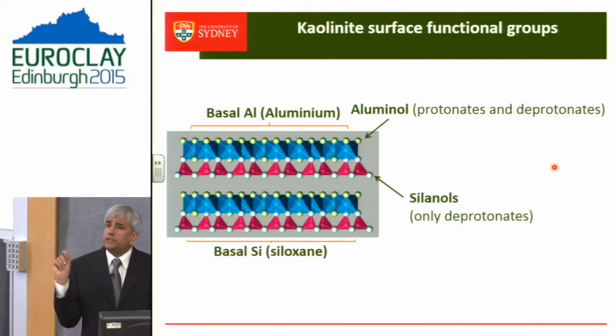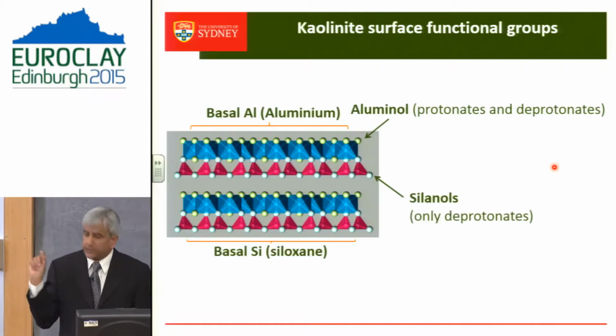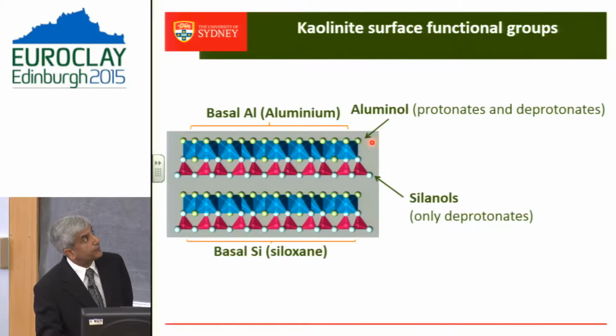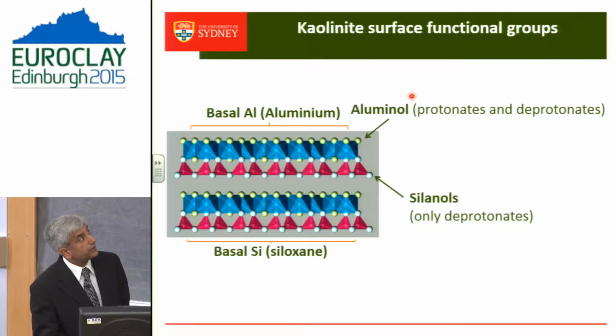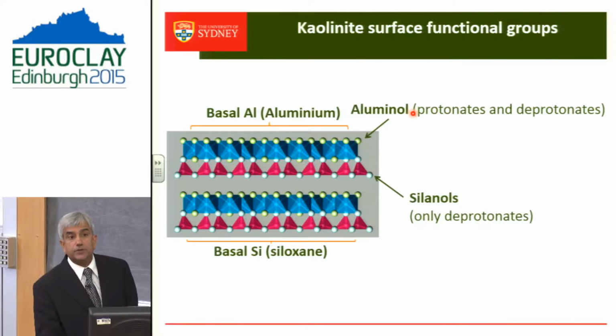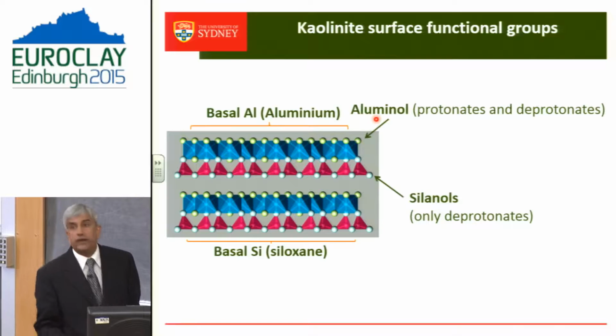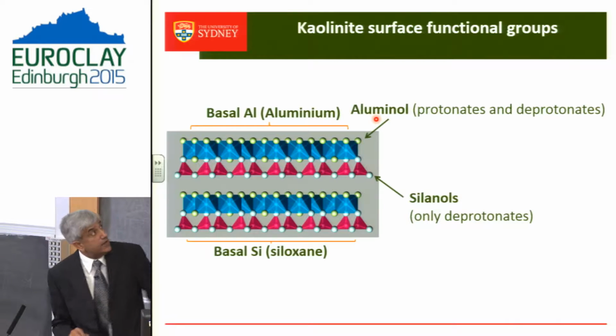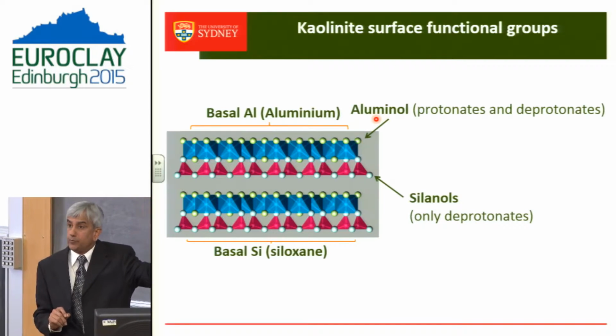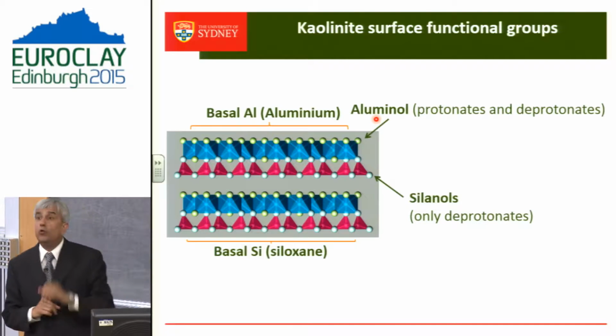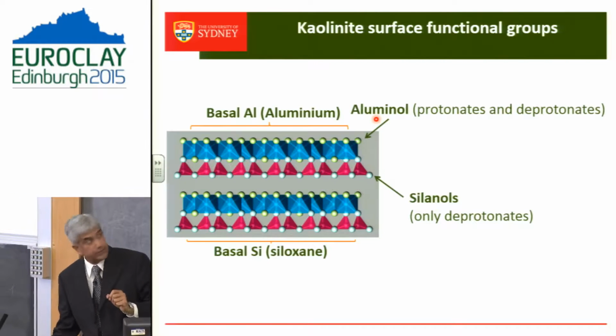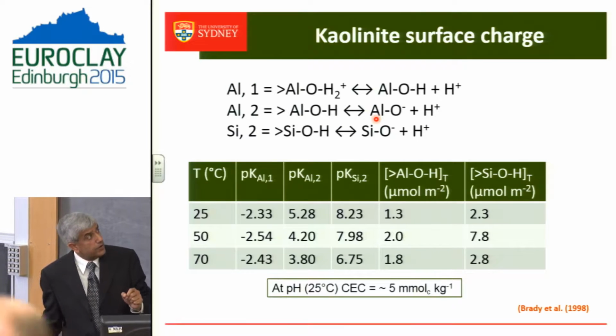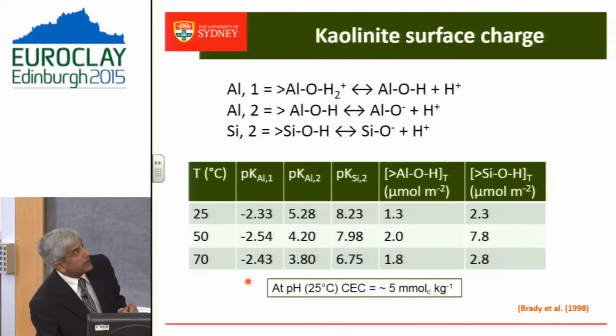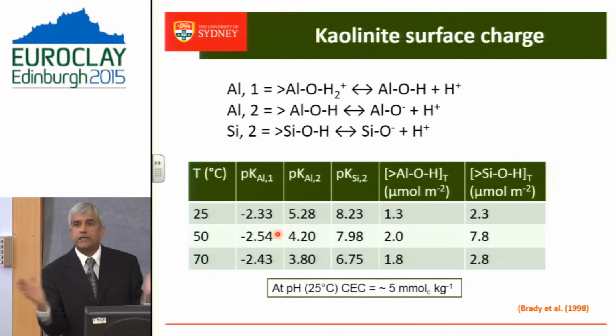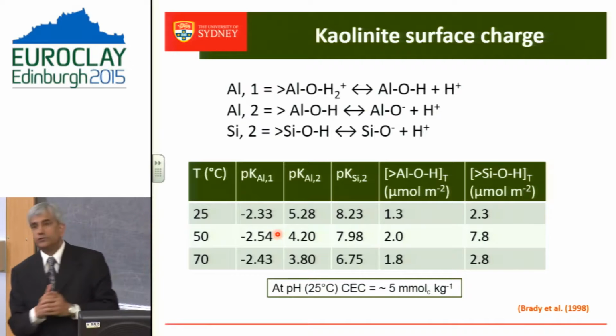In case of kaolinite, there is very little permanent charge in the structure. Most of the activity comes from these two functional groups on the edges of the particles, aluminol and silanol. Okay? Aluminol can protonate and deprotonate, whereas silanol only deprotonates. What happens as a result of that? So we have different pK values for these functional groups. These aluminium functional groups dissociate at much lower pHs compared to the silicon groups.